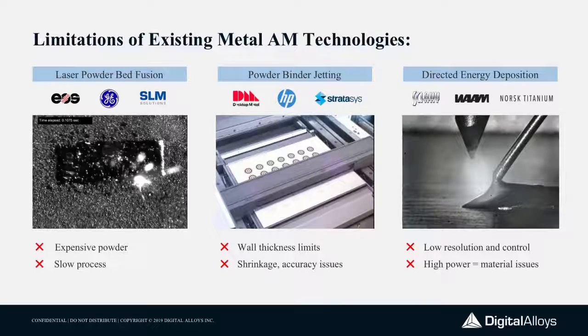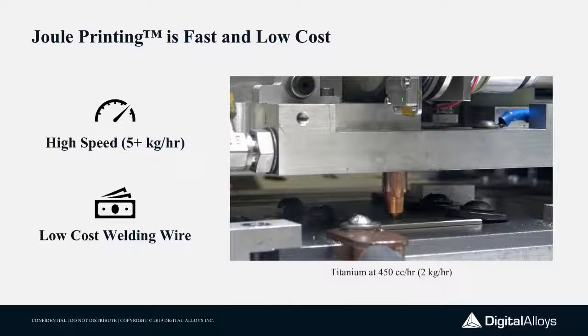So what we do, Joule printing, and this video is in real time, is we take a wire, and I already mentioned some of those benefits. It's relatively low cost, it's safe, you can find it in a lot of different metals thanks to the welding industry. We take that wire, we touch it to the build plate, and then we push electric current through it. It's quite different than what most people think of as arc welding. It's really differentiated from arc welding in the sense that there's no arc. We're pushing current directly through the wire, so we're using resistive heating, just like a coil in a toaster, to rapidly melt the tip of the metal wire in contact with the part.